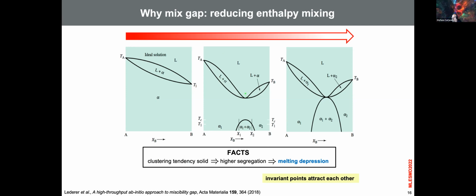If you look at the phase diagrams, and I've been looking at phase diagrams for ages, you actually see that these points tend to be below these points, right? So the melting depression goes down, right? And the minimum of the melting, which is called the congruent melting, is usually near the same composition of the highest critical point of the miscibility gap, okay? You can play this trick more and more. You can increase the height between A and B and B and A. So a miscibility gap is going to go up until they touch, and this forms the eutectic phase diagrams, or eutectoid if this were solid. Okay. So why are we interested in this?